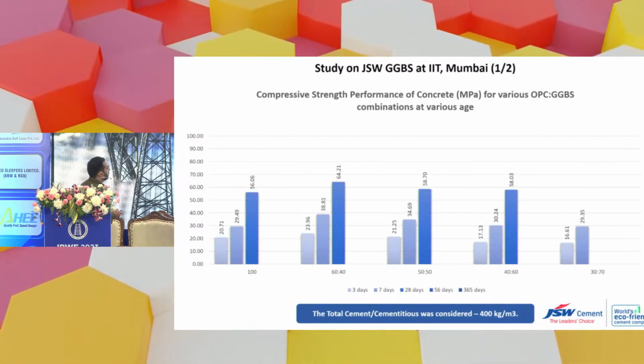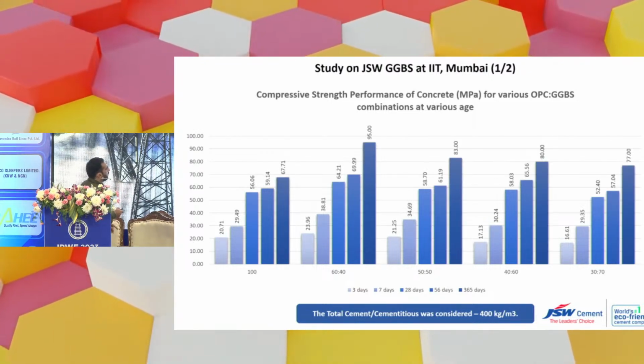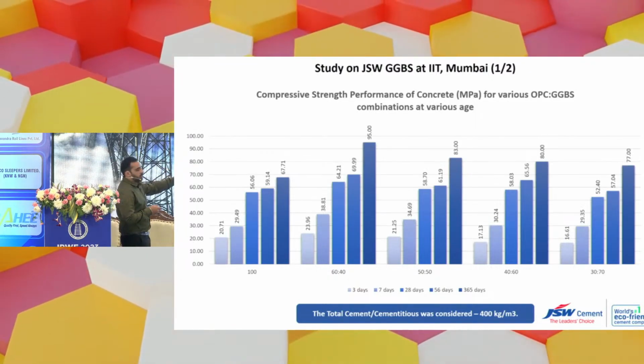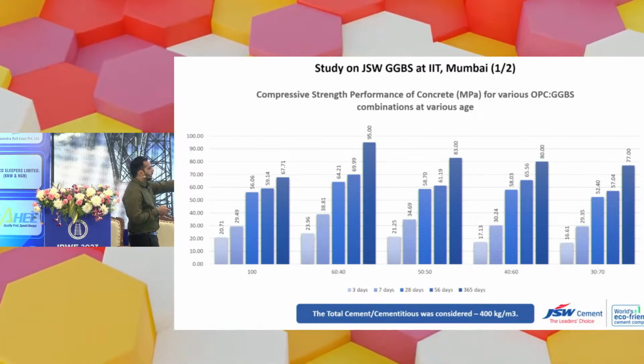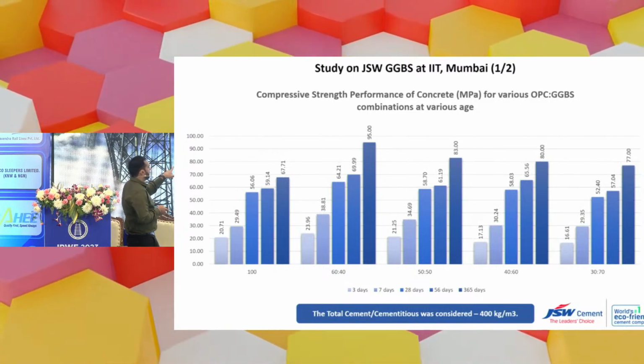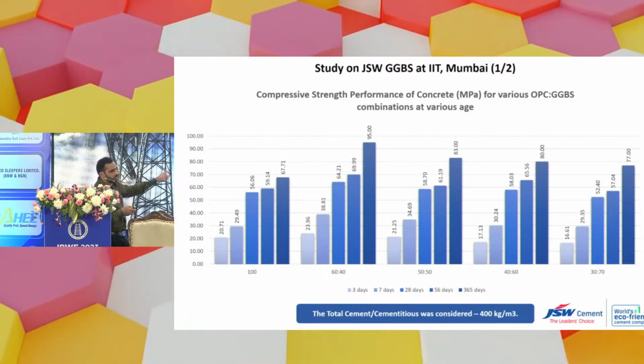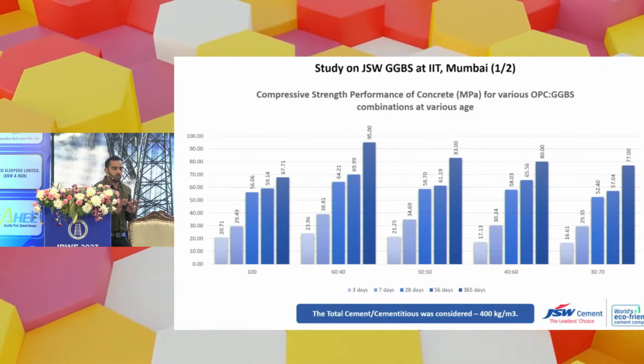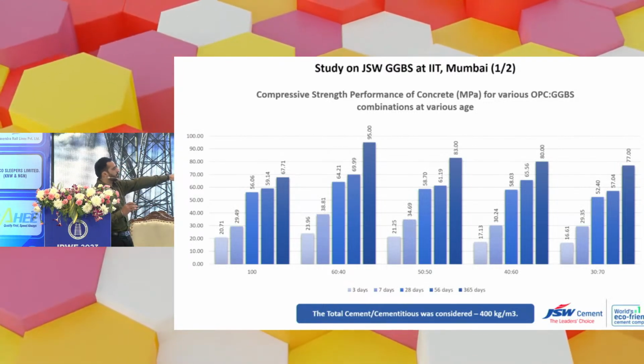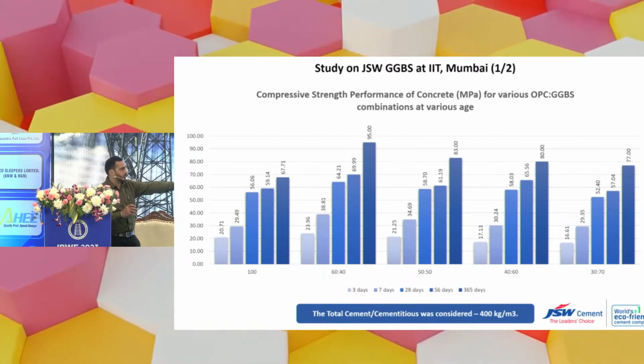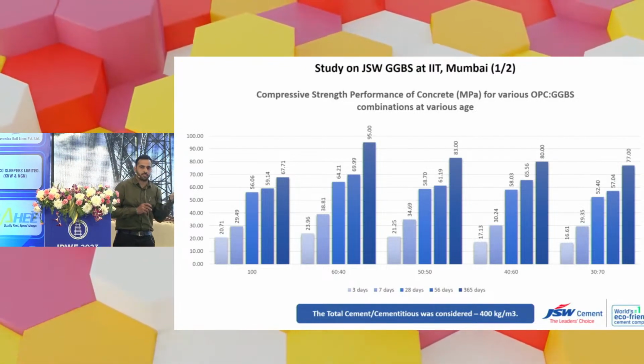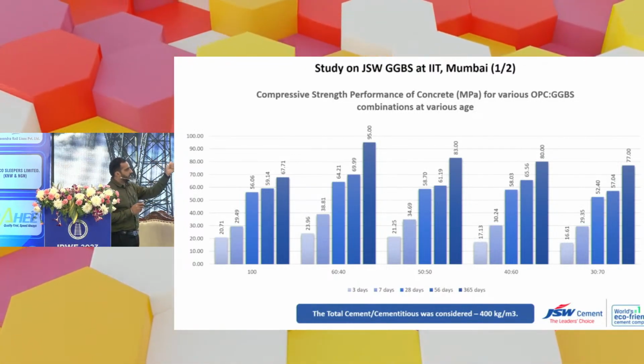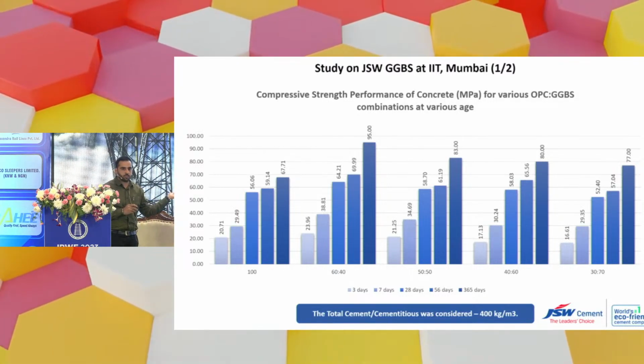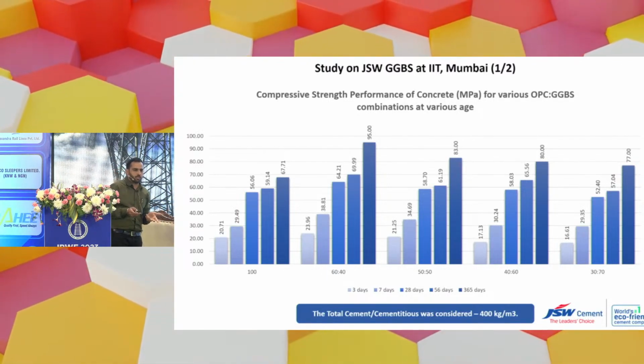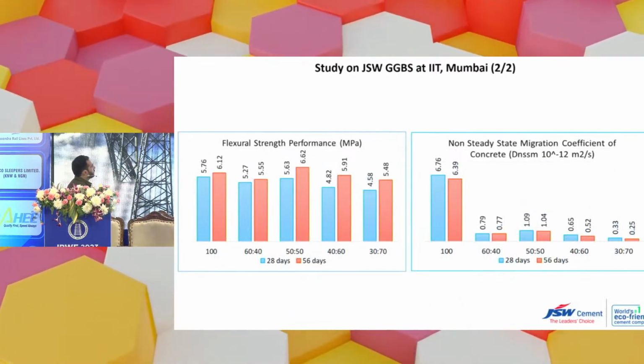This is a very interesting study conducted by IIT Bombay. We have a short time, so I'll quickly update on that. IIT Bombay conducted testing at 3 days, 7 days, 28, 56 and 365 days. 100% OPC at the age of 365 days provides a strength of 67 MPa. They did trials on 400 kg cement with various replacements: 60-40, 50-50, 40-60 and 30-70. The 100% OPC strength at 365 days is lesser than what 70% GGBS and 30% OPC has. Any structure we make is for the long term only. So this is the flexural strength.